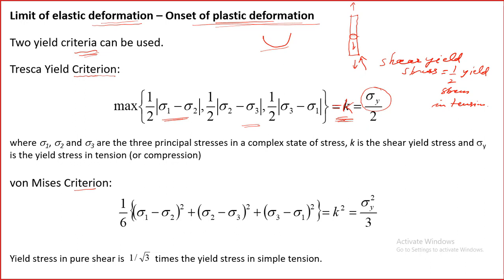And the von Mises criterion is a little bit more complex. It is a combination of the principal stresses in this way. This is given as K squared, and this comes out to be sigma y squared over 3. Again, sigma y is the same, the yield stress in the tensile test. So using the von Mises yield criterion, we can give the shear yield stress by this equation.